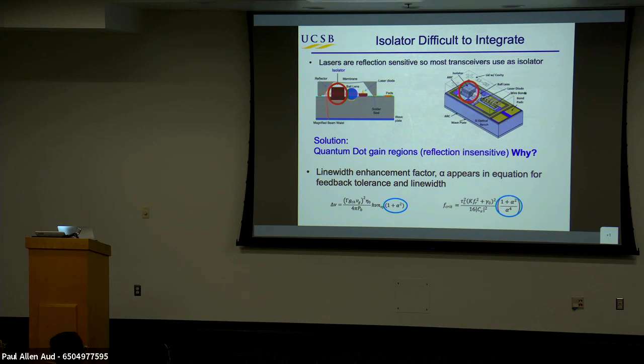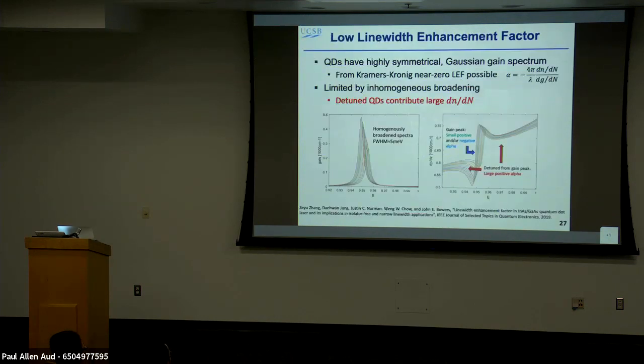If alpha is small, we can neglect this. This is what matters. And typically quantum well devices have alphas of 2 to 4. With quantum dots, you can easily get them to under 1, and recently we've got it down to below 0.1. So at 0.1, you're literally 10 to the fourth times less sensitive than you'd expect for a normal quantum well device. And that's what you'll see.